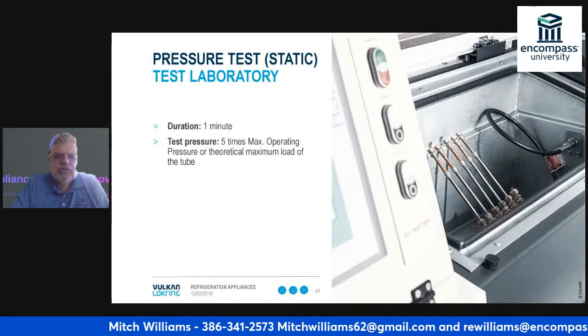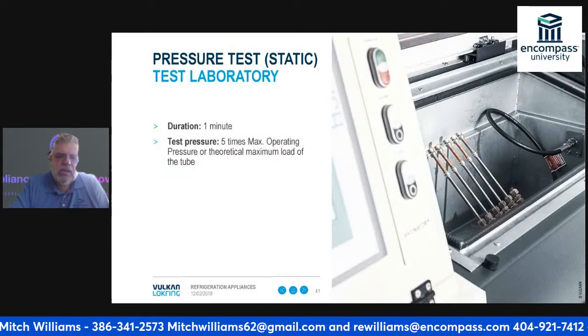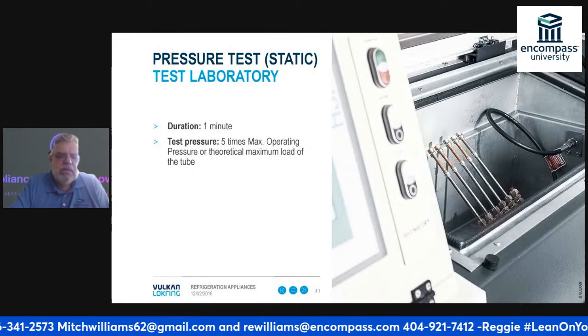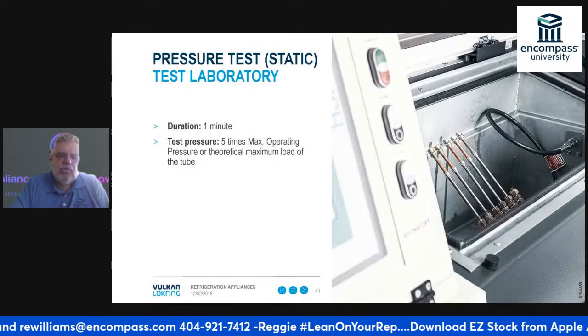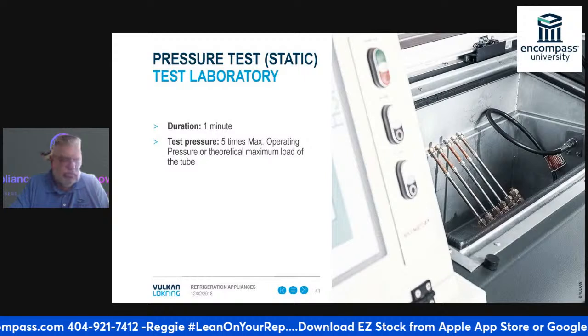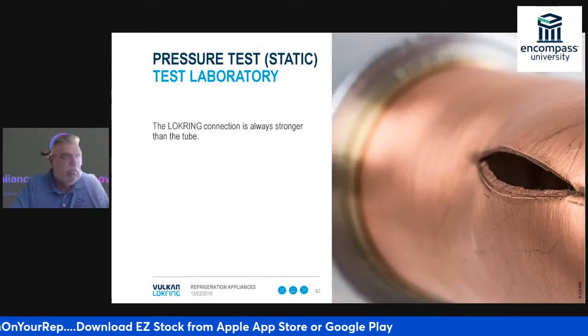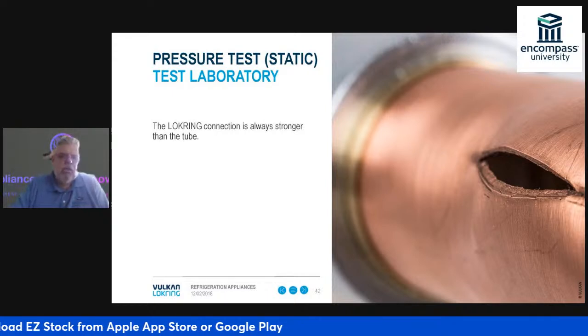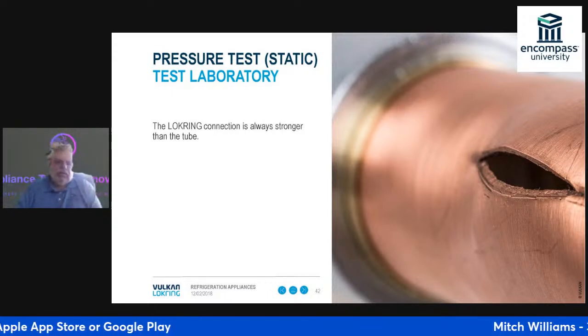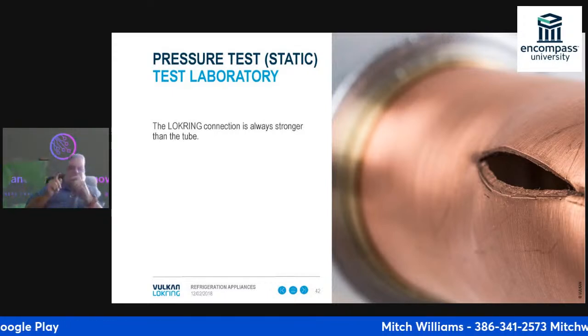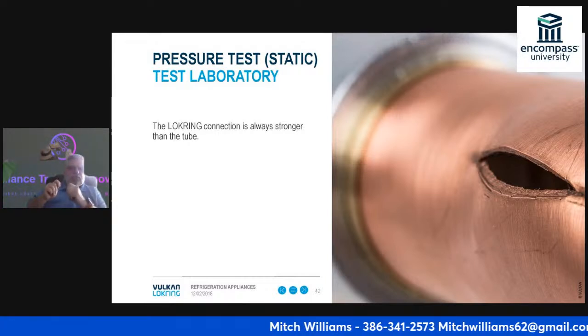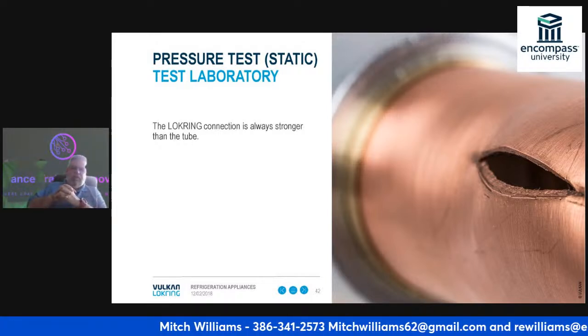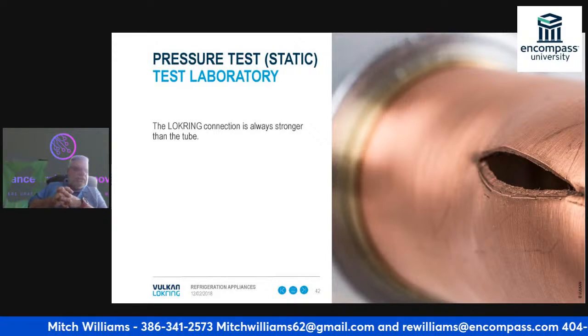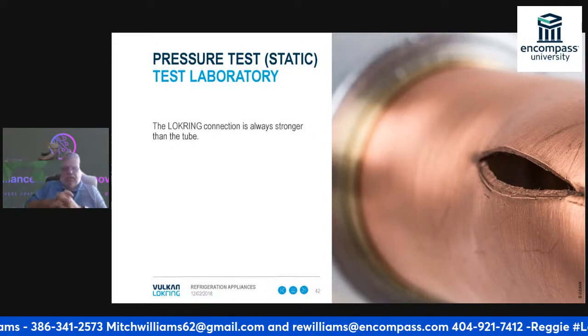Then we go to the pressure test, static pressure test. That lasts for 1 minute. It's 5 times the maximum operating pressure or the theoretical maximum load of the tube. Whenever they do these, they actually will blow. They have had the tubes blow, which is shown right here. Okay. The Lokring connection has always been found stronger than the tube itself. It's the tube that splits, not the Lokring connector.